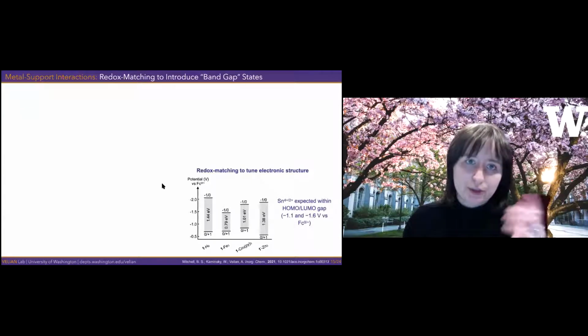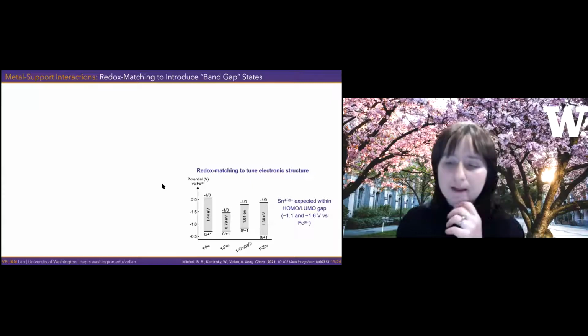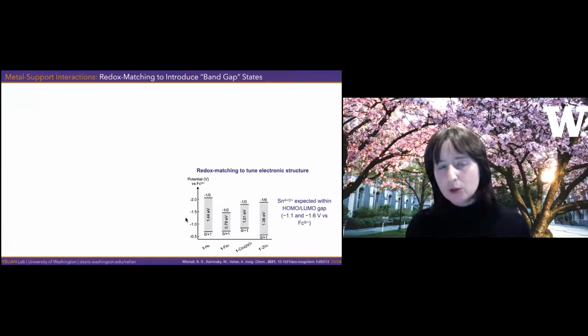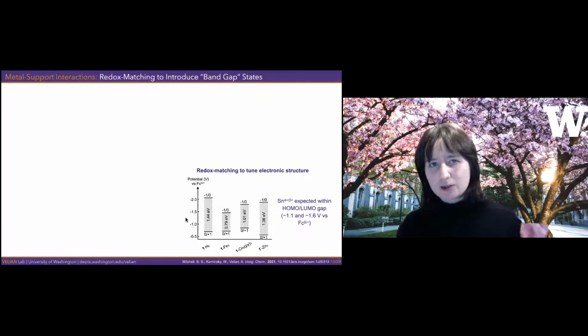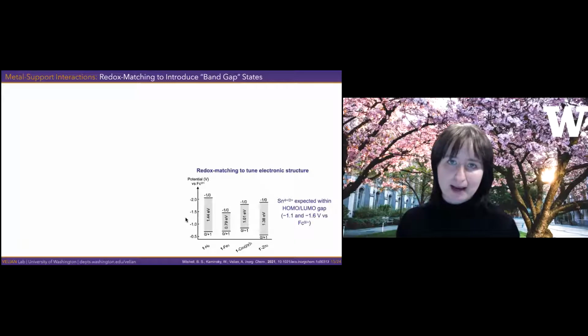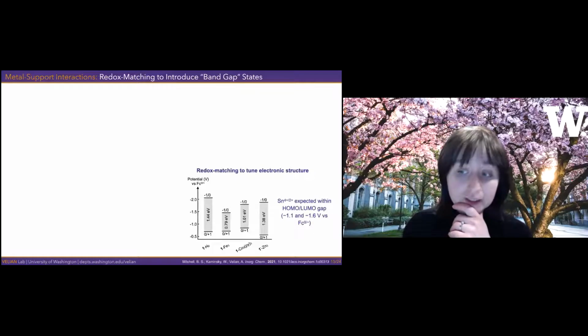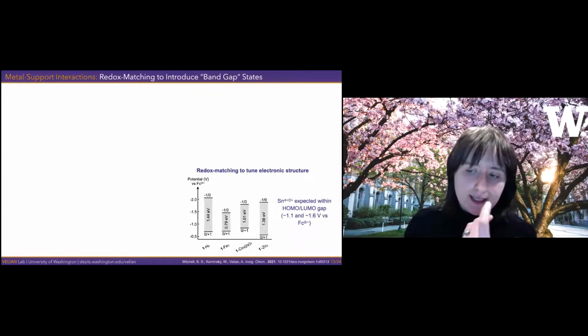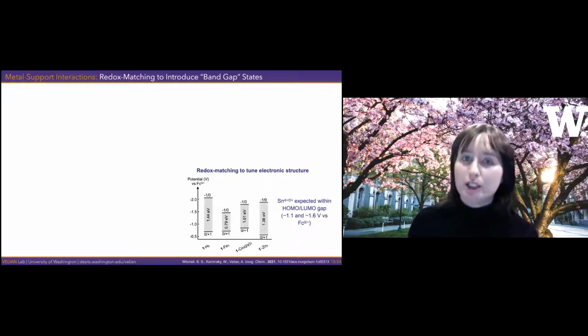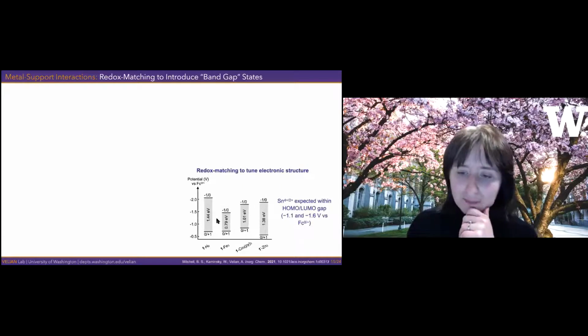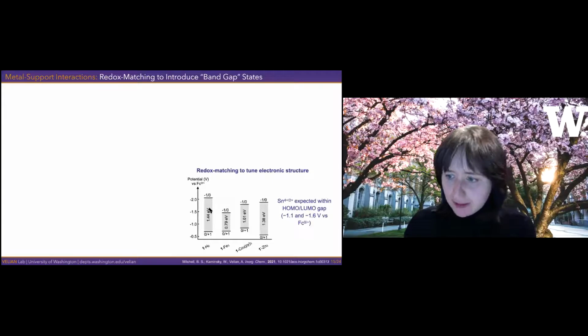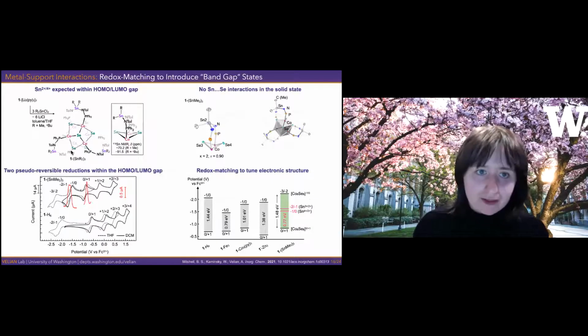Here's another strategy to do that. We thought, okay, one way to take a wide bandgap semiconductor and change its electronic properties is to dope it with something that is redox matched with its band gap. So we applied a similar strategy here, and we took tin. If you look at where tin 4 to tin 2 reduction might occur, you see that it overlaps really nicely with the band gap of our cobalt core. And we set out to do it in the lab and found that our hypothesis was confirmed.